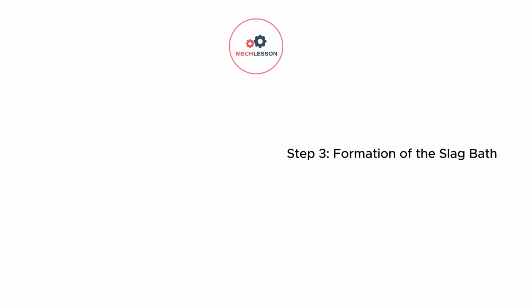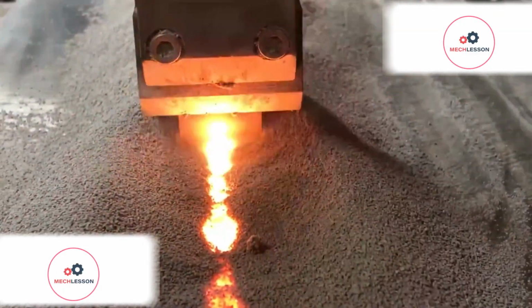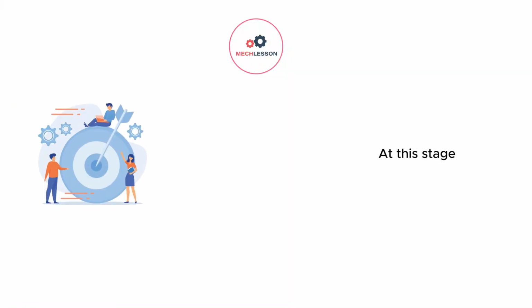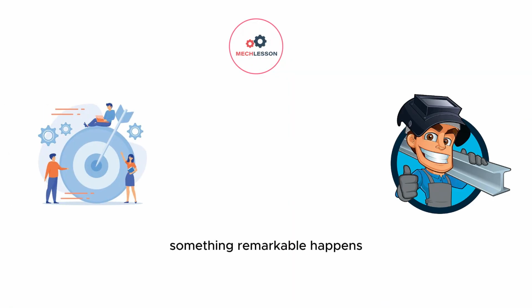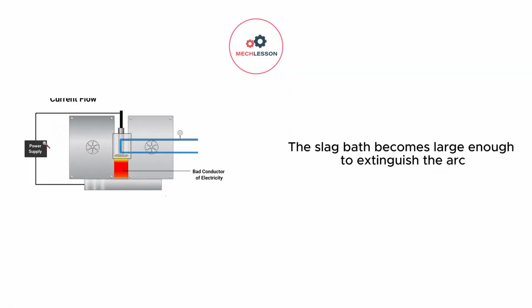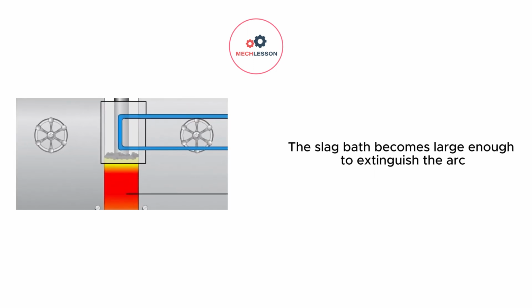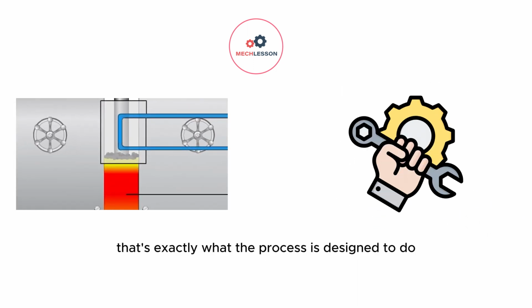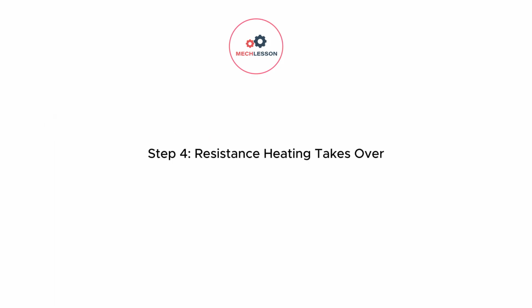Step 3. Formation of the molten slag bath. As more flux melts, a pool of molten slag develops. This molten slag becomes electrically conductive. At this stage, something remarkable happens. The slag bath becomes large enough to extinguish the arc, and surprisingly, that's exactly what the process is designed to do. Step 4. Resistance heating takes over.